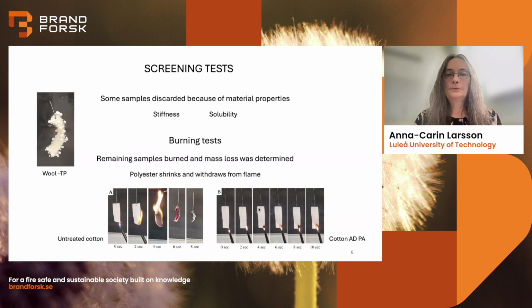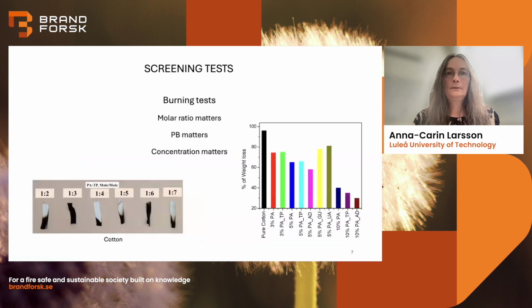This was a quite okay method for cotton, but for polyester it's known that it shrinks and withdraws from the flame, so it was a bit difficult to trust those results from the burning tests. But we can see, at least for cotton, some results here — pure cotton lost almost the full weight.